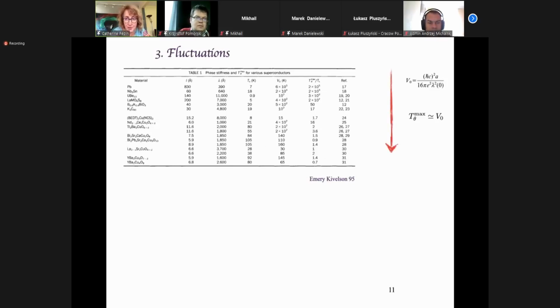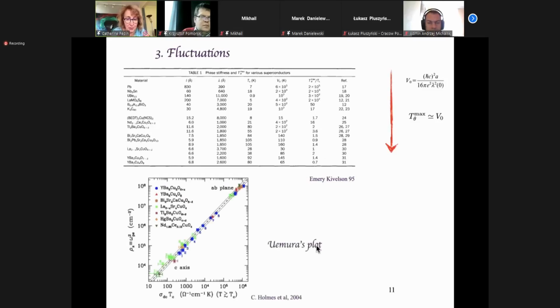And there is strong experimental evidence for that, which we call the Uemura plot, revived by Chris Homes in 2004. Later, you have a good version of this plot. So you plot the superfluid density here as a function of TC, and you see it's beautifully linear in T, which is typical of a BKT transition. This is basically the most experimental proof that we have vortices, anti-vortices, and fluctuations at TC.